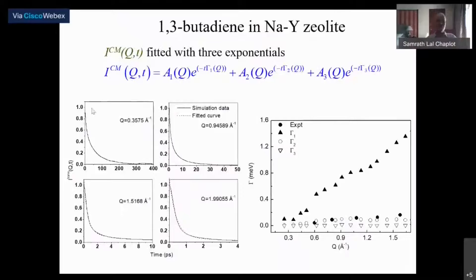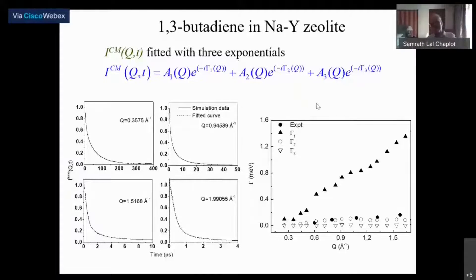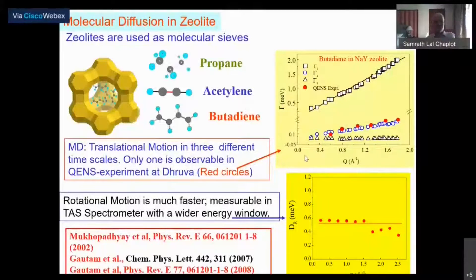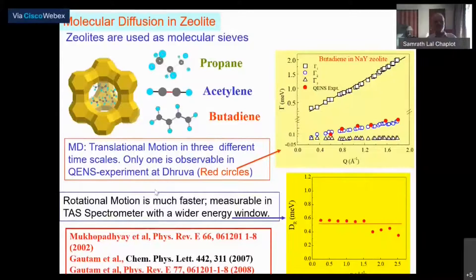This was just an illustration: you do the molecular dynamics simulation, get the position-time correlation function, do a Fourier transform, and see whether it can be fitted with a single Lorentzian or more Lorentzians, or sometimes even with a Gaussian kind of term. That is the modeling of what is simulated, and then you can compare with experiments. It turned out to be very good agreement. The classical force field used here was quite good.